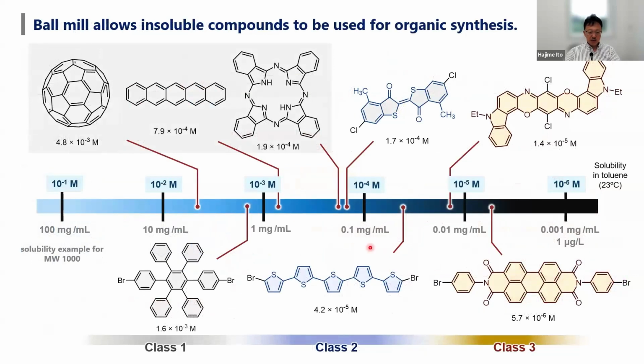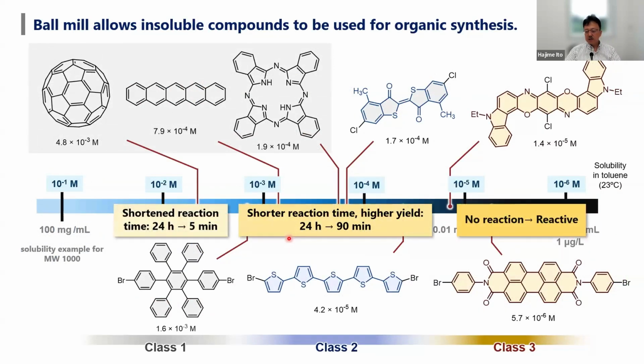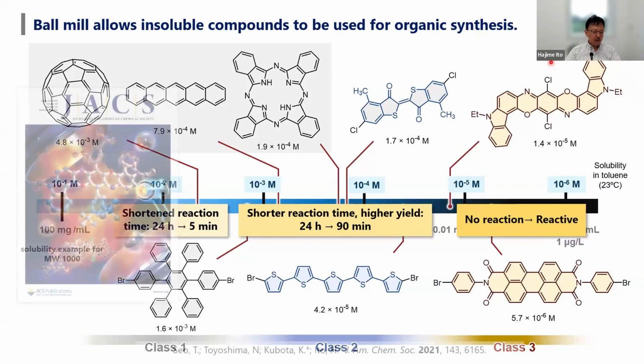We also checked the reactivity of other insoluble materials, and found that even compounds 100 times less soluble compared to carbon 60 can be useful for cross-coupling reactions in ball milling. Of course, this is impossible in previous solution phase reaction systems.